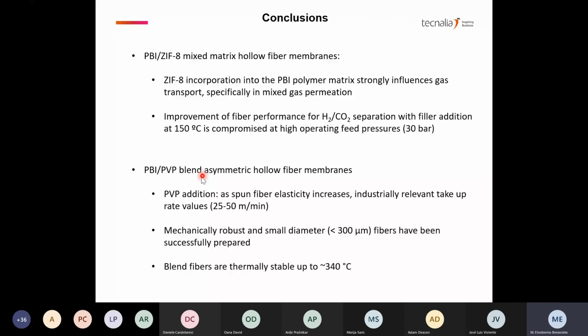And also we demonstrated that by the addition of polyvinyl pyrrolidone to the PBI, the spun fiber elasticity increases, and this results in a significant improvement in the take-up rate. So we managed to increase the take-up rate until industrially relevant values. And we prepared some PBI-PVP blend fibers, which were mechanically robust and with a diameter smaller than 300 micrometers. We also showed that blend fibers are thermally stable up to 340 degrees C. So they are stable at typical temperatures of pre-combustion CO2 separation.